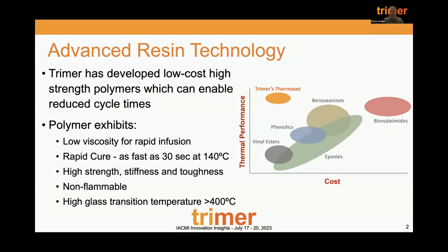What we have is a very low cost system. It is an automotive kind of pricing system, but we can achieve aerospace grade properties. We can generate glass transition temperatures better than polyimides. We have a low infusion viscosity, so we can very rapidly shoot parts, either through HPRTM, RTM, or VARTM. We have resin systems that are suitable for bath pultrusion as well as injection box pultrusion, offering some of the fastest line speeds that are available.